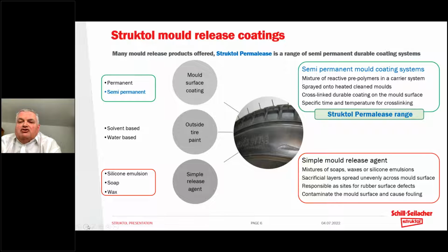Alongside that, then we can think about the so-called semi-permanent coatings. And this is a very interesting area where we can extend the lifetime of the mold between cleaning by applying a reactive coating onto the surface of the mold in order to prevent the buildup of mold fouling, to really seal the mold and to have an almost inert coating that prevents then the adhesion and subsequent fixing of the mold deposits onto the surface of the mold. So really we can contrast the very simple release agents, which can contribute also to mold defects, as you see in the picture, with the permanent and semi-permanent, as we would talk about here, much more durable and longer lasting coatings. Next, please.